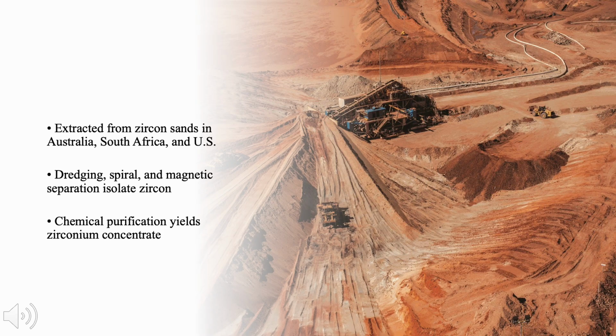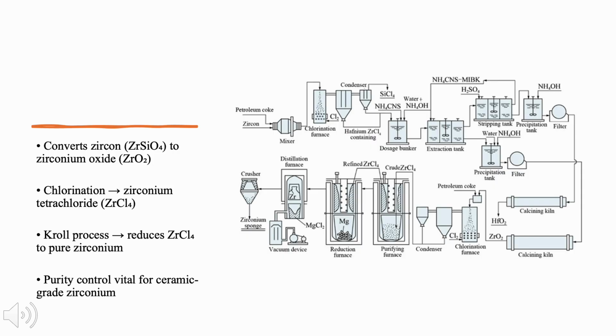mining is complete. Once the zircon sand reaches a refinery, the next goal is to extract pure zirconium. The photo here shows part of a chlorination system, the starting point of the refining process. Chemically, zircon is zirconium silicate, a stable compound that needs to be broken down to isolate zirconium. So in the chlorination stage, zircon reacts with chlorine gas and carbon at around 900 to 1,000 degrees Celsius. This reaction produces zirconium tetrachloride, a volatile compound that vaporizes easily.